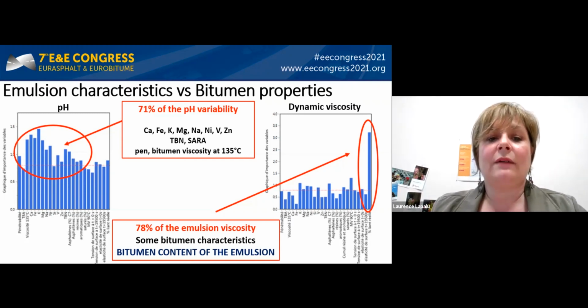If you look at the graph on the left, you can observe that 71% of the pH variability is linked to the bitumen. And it is linked to the element contents, to the total basic number of the bitumen, to the Saturates fraction, the penetration, and the bitumen viscosity at 135 degrees Celsius.